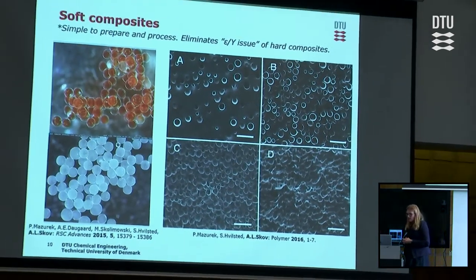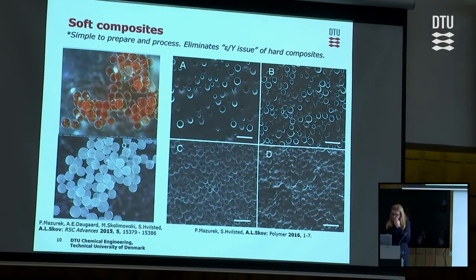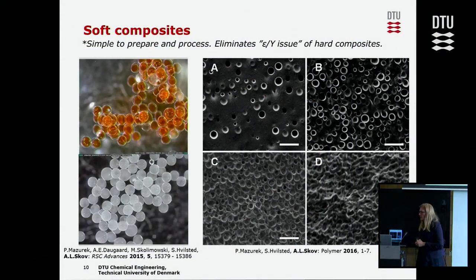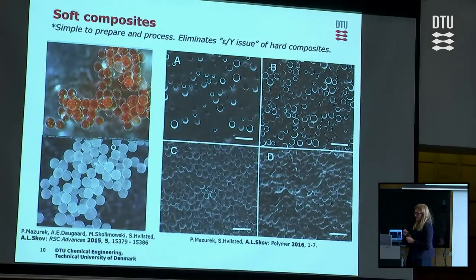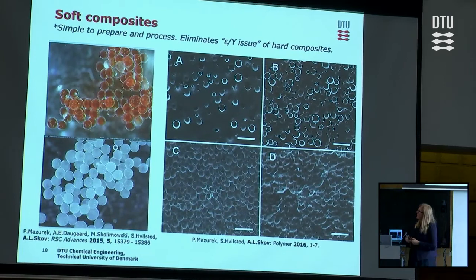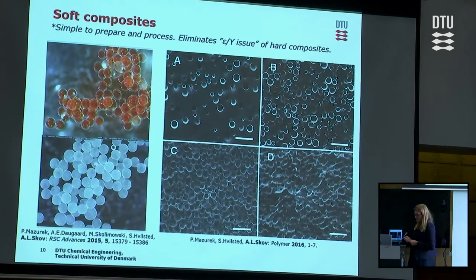So we also had the idea, instead of adding these hard, rigid metal oxides into our systems, we would like to have some soft materials embedded in the material. And we spent a lot of time initially using microfluidic devices, and we made these very nice capsules. So we have a silicone shell around the liquid, and then the silicone shell could be reacted into elastomers, but the process was really tedious.